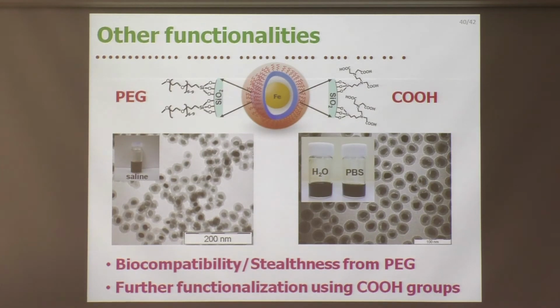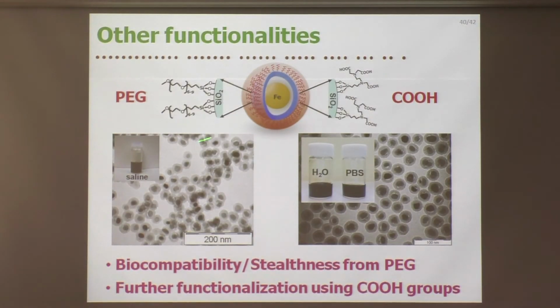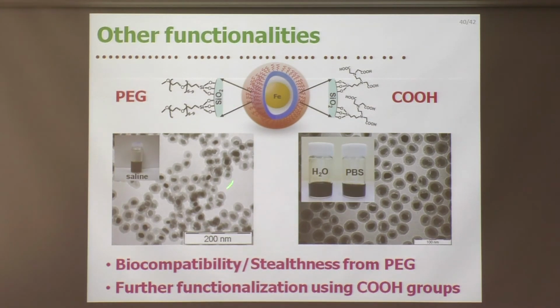In the previous slide, I explained the case of alkyl chains, but the range of surface functionalities is not limited to that. Here are other examples. For instance, we can get PEG, polyethylene glycol, modified samples—this is a TEM image. As you know, PEG is a biocompatible polymer and provides stealth properties for intravenous administration.